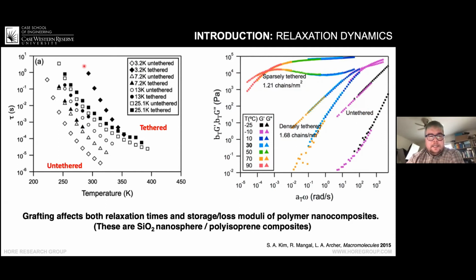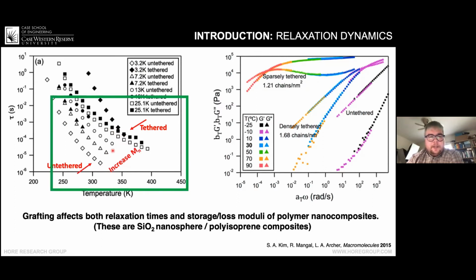Corresponding to that, these researchers measured the relaxation times of the chains. And if you just focus on these diamonds here and these diamonds here, the black diamonds are the tethered chains. The open diamonds are the untethered chains. And you see that the relaxation time of the tethered chains is much longer than that of the untethered chains. But as you increase the molecular weight, these differences start to disappear and the 2 sets of lines start to approach each other.